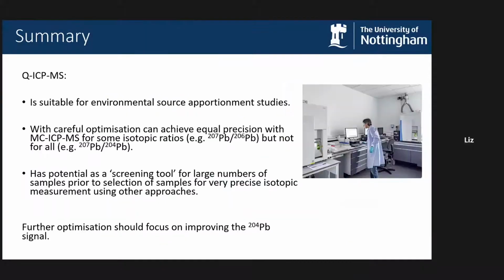Okay, that was a slight aside. So I just want to say in summary, quadrupole ICP-MS is definitely very suitable for environmental source apportionment studies, but with careful optimization, it can achieve equal precision with the multi-collector ICP-MS for some isotopic ratios, but perhaps not for all. So ratios with lead 204 are less successful. But despite that, it does have potential as perhaps a screening tool where generally more precise isotopic ratios are needed.